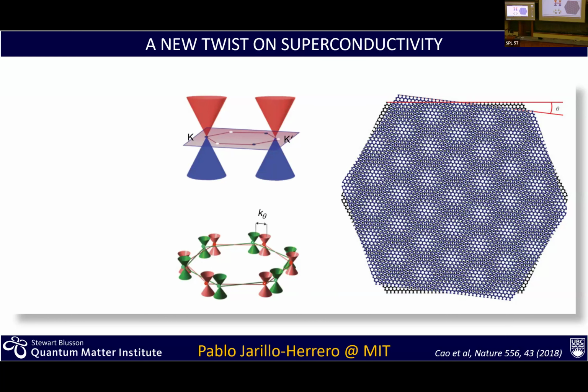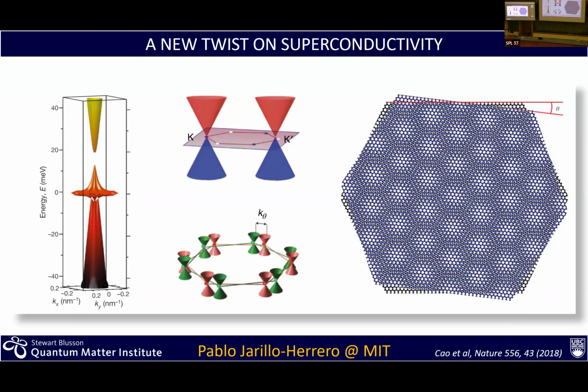It's a bit like having a molecule, and all of a sudden the 2 atoms are close enough and they form bonding and antibonding levels, no longer 2 degenerate levels. And so what happens next is, instead of having 2 Dirac cones located at different places, all of a sudden you get a very narrow band where they touch. And that narrow band is very interesting, because the narrow band means that you have increased your electron density in momentum space by making them very much confined in energy. So now graphene is a non-interacting system, but as you increase the electron density, even a small interaction becomes significant, and this material becomes a superconductor. So it's really almost electronic engineering, engineering electronic structure at its best, just simply changing the angle.